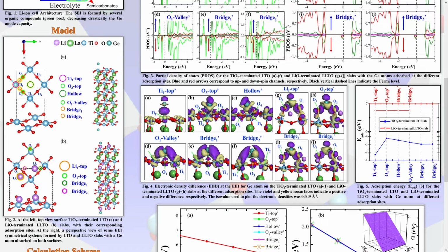Figure 5 shows the adsorption energy, which indicates how adherent the germanium is to the surface of the substrate in the different cases studied. For the lithium-free perovskite with titanium dioxide termination, the germanium is more strongly bound at the oxygen top site. However, the germanium remains more strongly attached to the lithium oxide termination than in the case of the titanium dioxide surface.